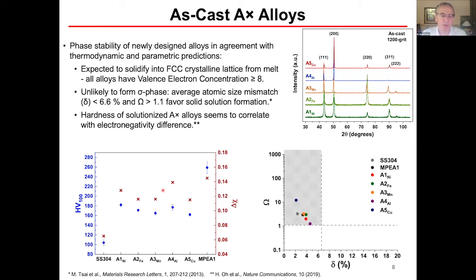So here I'm showing the Vickers hardness for the solutionized materials. Again, I'm not showing what happens when we harden them by precipitation of phases, but indeed the solid solution strengthening provides some added hardness relative to, say, 304 stainless steel, and it seems to correlate with this electronegativity difference.